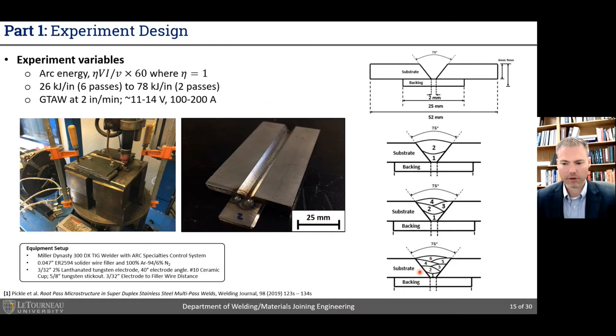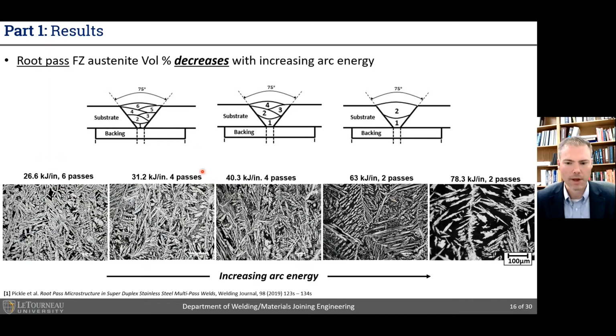We focused in particular on the root pass under the idea that this would likely be the location that might be in contact with a corrosive media. And what we found was a somewhat unexpected result.